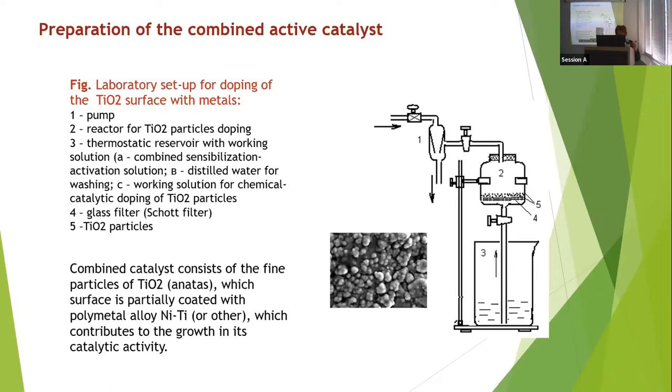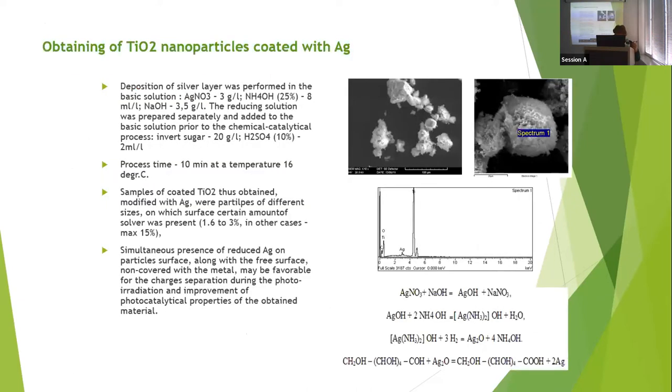on this slide. We have found that the combined catalyst consists of fine particles of the anatase form of titanium dioxide, whose surface was partially coated with a polymetal alloy, in this case nickel titanium or other, which contributes to the growth of its catalytic activity. In our experiment, we have managed to deposit a thin layer of silver on the surface of the nanoparticles.